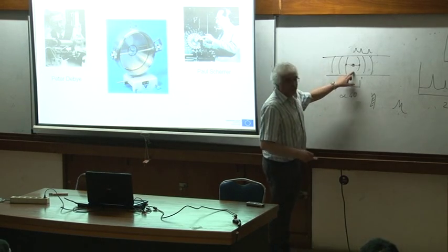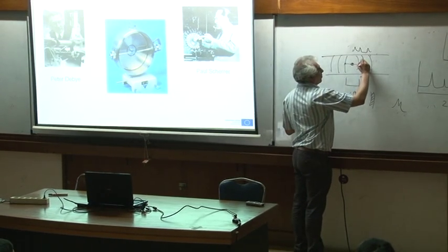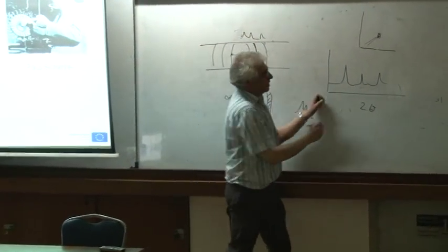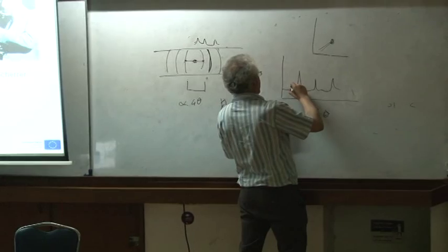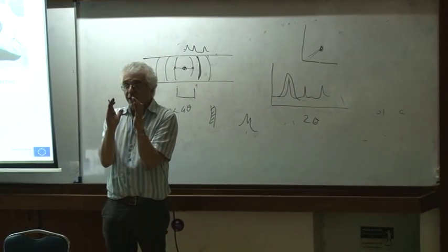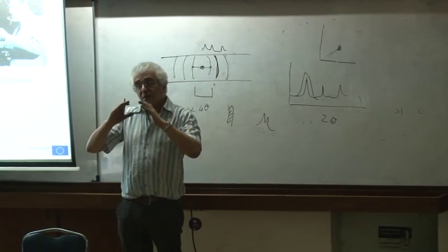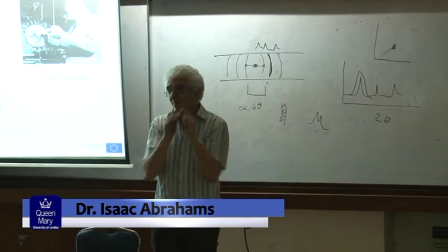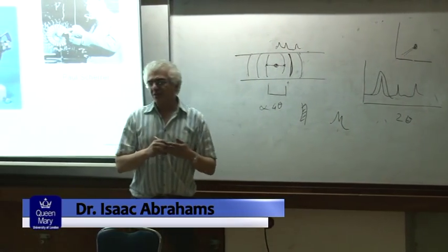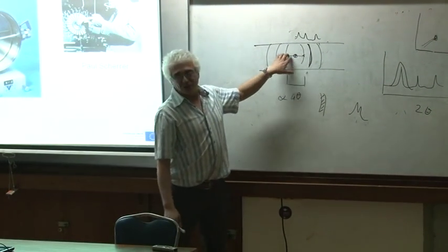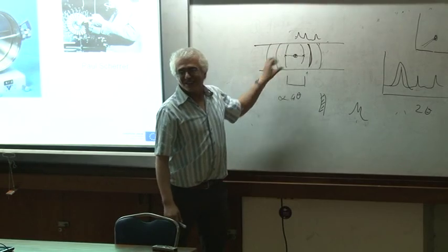So all that happens in this is that you have wider lines. So this looks a bit wider on here. The same thing here. So this would be a slightly wider pattern, like this. So the smaller the crystallite, the wider the pattern. The better the crystallinity, so the larger the crystallite, the narrower the lines. So there's also an instrument resolution factor, and the instrument resolution of this is much poorer.